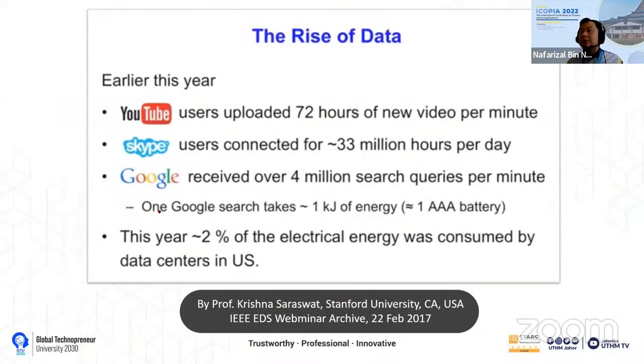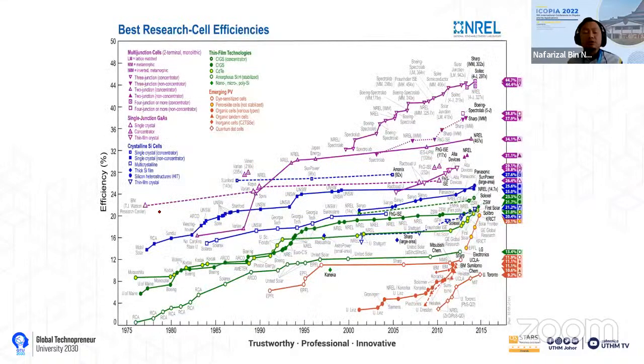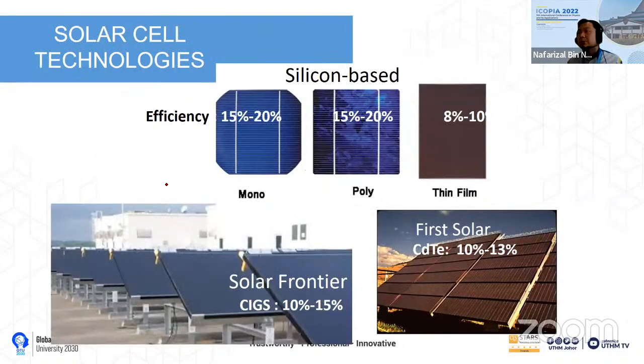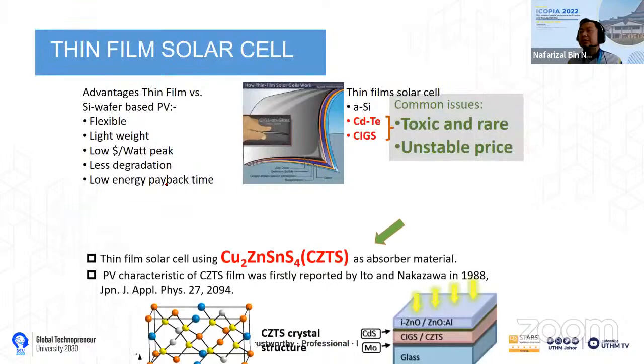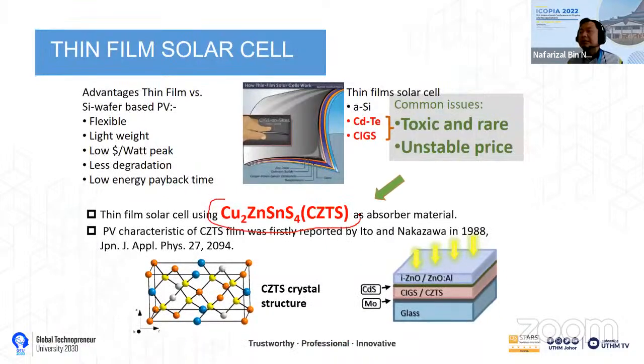So we use this one for the growth of solar cell material actually. The solar cell material that we want to focus on for this project is what we call CZTS: copper, zinc, tin, and sulfur. CZTS is a new material to replace the existing CIGS material, because CIGS, the existing thin film solar cell, uses a rare material, not abundant. So we want to replace it with a more abundant material. So we call it CZTS here.